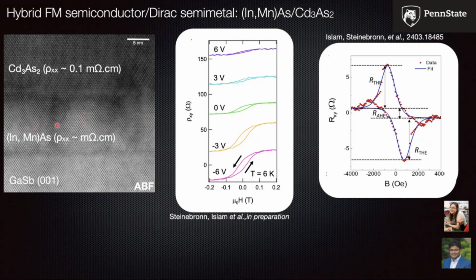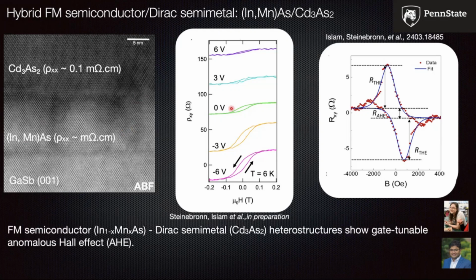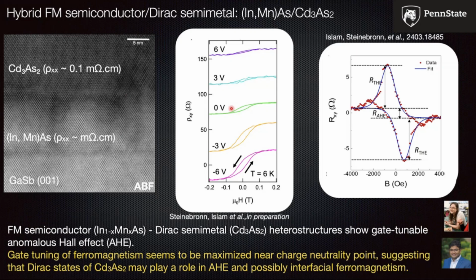So here is a TEM image of manganese-doped indium arsenide with cadmium arsenide on top. And you see a nice heteroepitaxy. And what happens here is that you actually form a PN junction in which by top gating and applying a bias, you can turn the ferromagnetism on and off. But equally interesting, you can also get signatures of what may be, and emphasize maybe, a topological Hall effect due to skyrmions. Again, the interest here is, can we image these? Can we get actual visual evidence for these objects? And we don't have that yet.